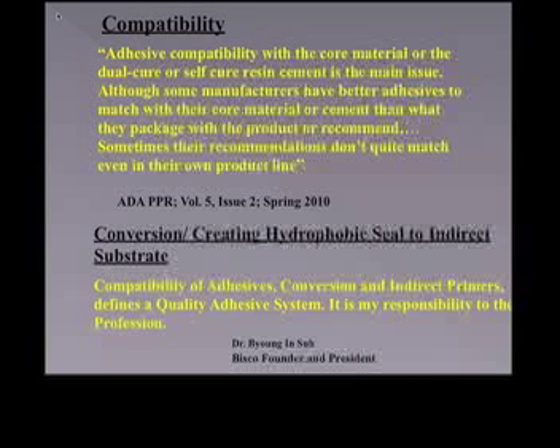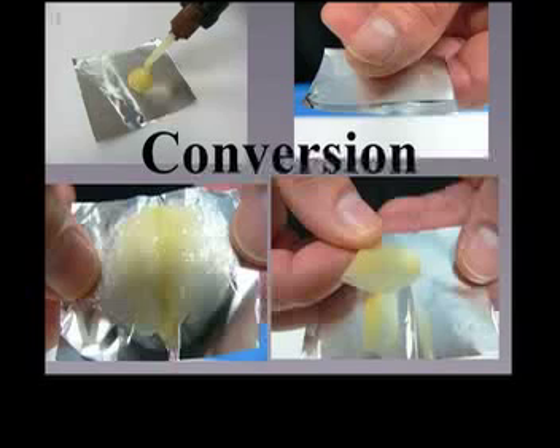We have to be aware that what our adhesives are and what cements we're using make a difference. If they're not compatible, we're not doing anything. So it's imperative that the clinician test the ability of their dual cure cement to self-cure. Self-cure mechanisms rule in indirect dentistry.